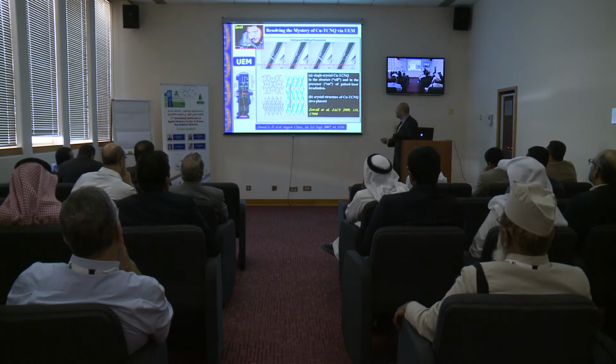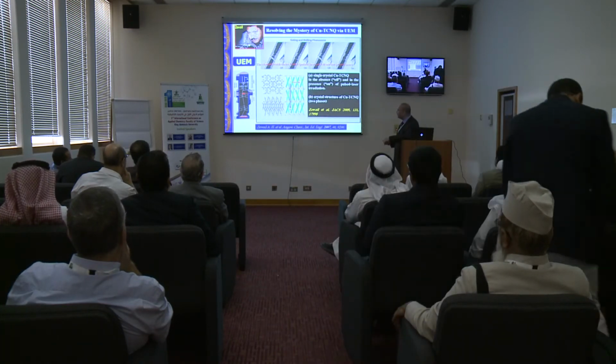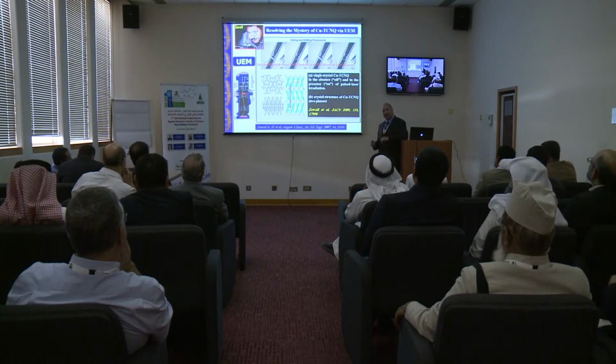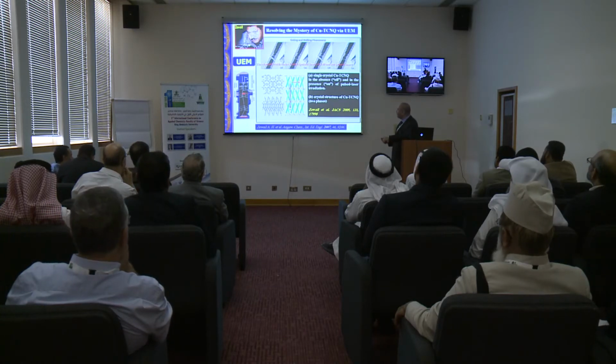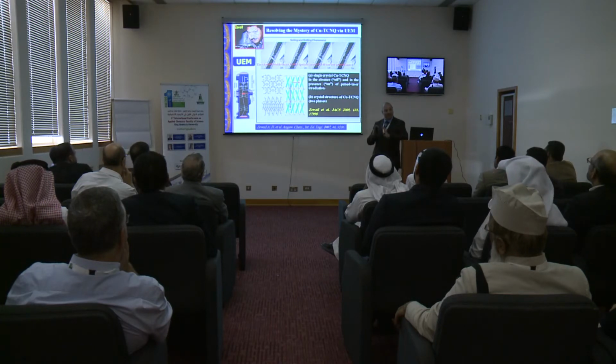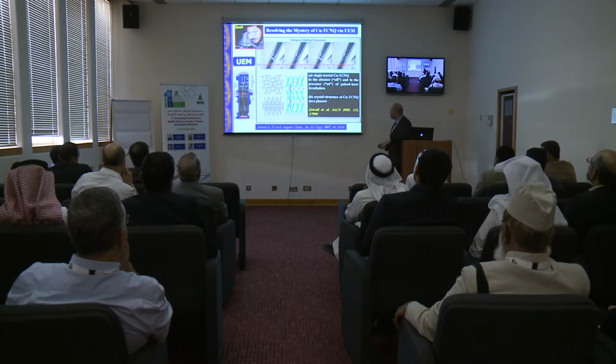Until the time of Zewail, who started to develop this ultra-fast electron microscope, and started to look at the crystals of copper TCNQ to resolve the mystery of that. He showed that when you have the normal crystal of copper TCNQ under high magnification of the ultra-fast electron microscope, they found there are cracks in the crystal. Along the whole crystal, there are cracks, probably around 10 angstrom. And those cracks actually make the crystal insulating. So that's why when you have two electrodes in there, it doesn't conduct any electricity.